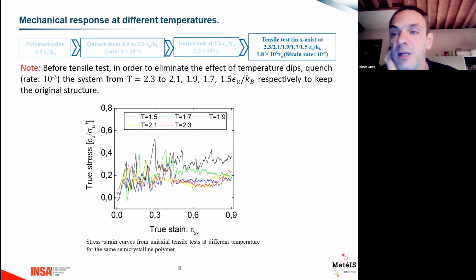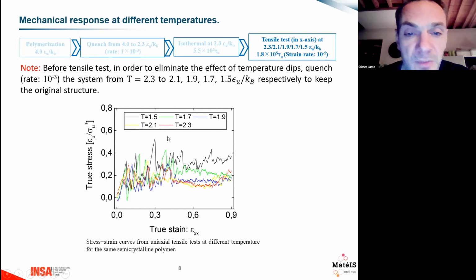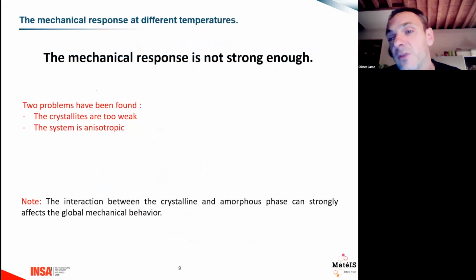Okay, so we have tested this system in terms of mechanical properties. It's just a tensile test that is possible to realize with these simulations. The tensile test gives these stress-strain results. This is the stress and the strain. And for the different systems I just showed before, obtained at different temperatures, we see that all the systems seem to behave the same, and it's very noisy also. In fact, there are two main reasons that show that our system has a problem.